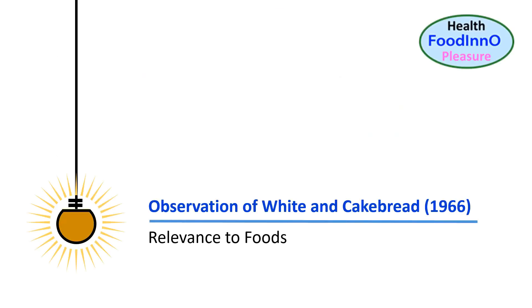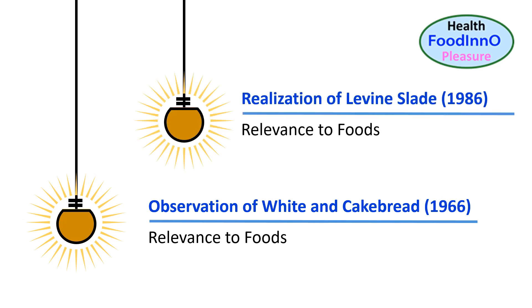In the case of sugar-based foods, British scientists Dr. White and Dr. Cakebread pointed out that sugar glasses are very unstable in the presence of moisture, and this instability under certain conditions can lead to various defects. For example, in a dry atmosphere, crystallization, graining, or collapse could occur, whereas stickiness, graining, or fluidity could occur in a moist atmosphere — mainly when products are stored above the glass transition. The significant applications of the glass transition concept in the 1980s emerged in food processing when Dr. Levine and Dr. Slade realized and identified major merits of glass transition. Many other groups around the globe generated significant data on glass transition and state diagrams.